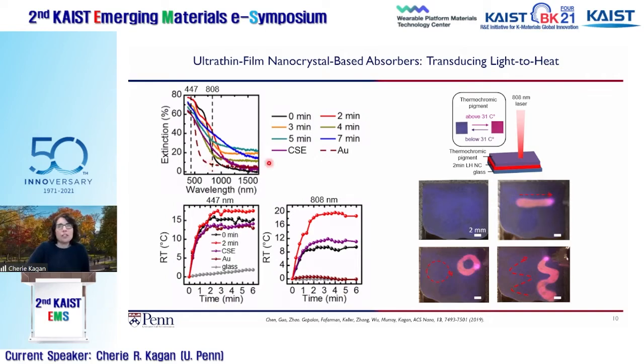We would shine a little laser pointer operating at, we did both 447 and 808. At 447, all the metals absorb, so if you shine light, it would heat up, and you could measure the increase in temperature. That's not true, obviously, for bare glass, which you'd expect to be transparent. But at 808 nanometers, your bulk metal film wouldn't absorb that light, it doesn't have extinction there, and so you don't see a rise in temperature. But by dialing in the ligand exchange and controlling how much, you could convert that optical energy into thermal energy and, even with a little handheld laser pointer, get things like 20 degree increases in temperature.